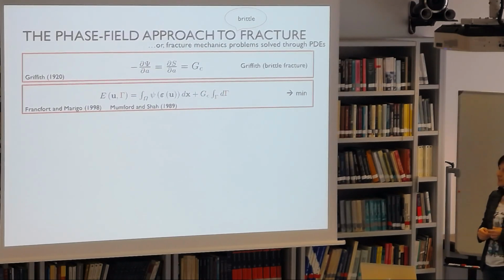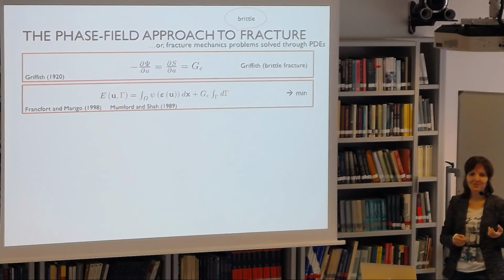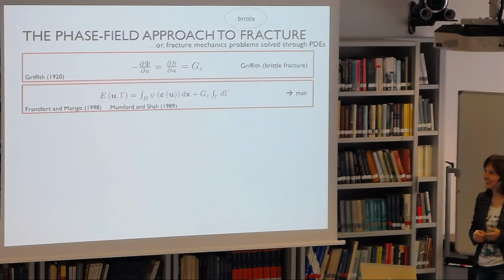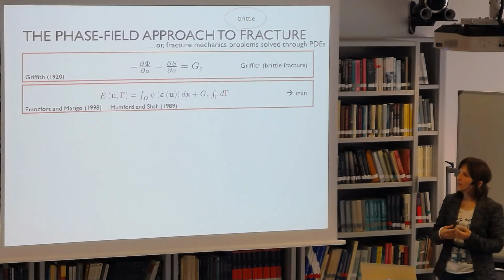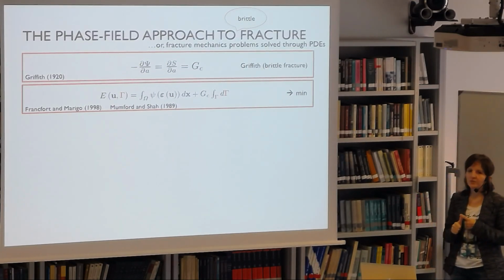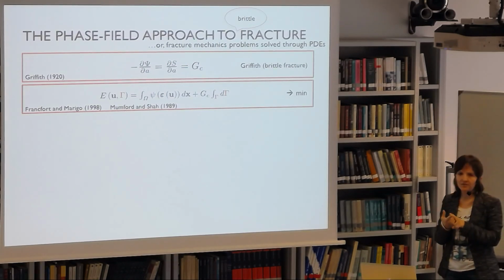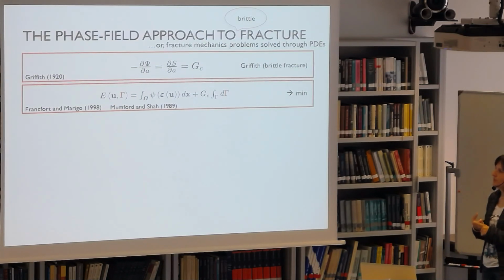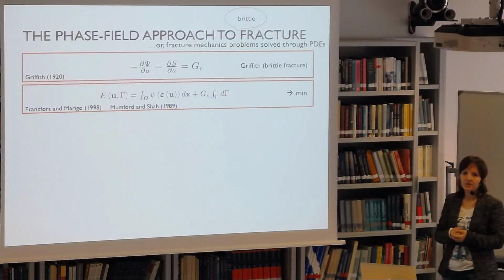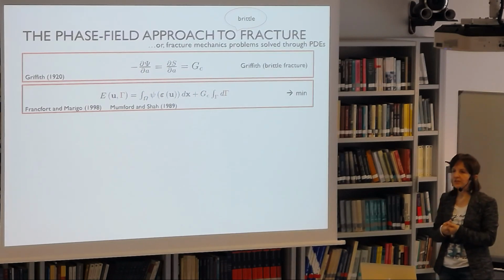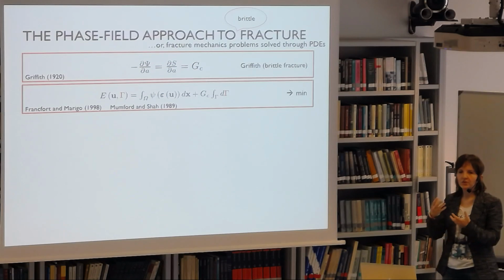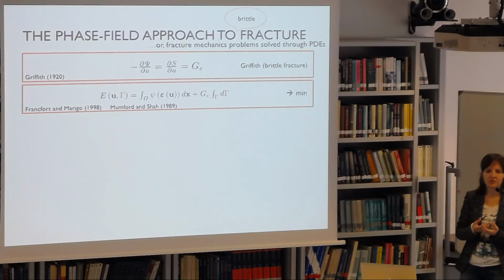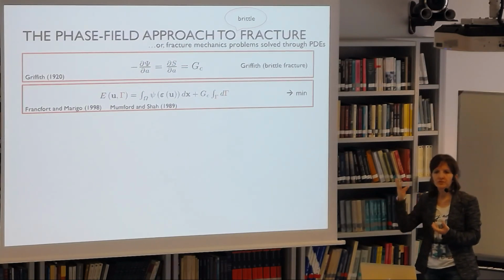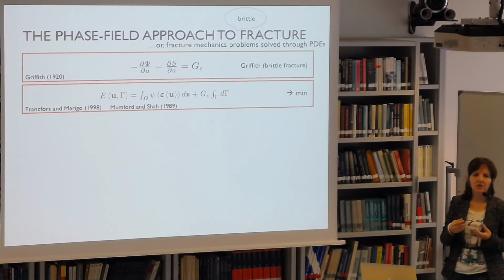Then at the end of the 90s, Jules Francfort and Jean-Jacques Marigo, who's probably very well known here, devised the variational approach to fracture. They basically recast Griffith's problem in the form of the minimization of an energy functional. Now, this energy functional has two arguments. One is u, the displacement field, and the other one is gamma, the crack set itself. So the energy functional is the sum of two terms. One term is the integral over the domain of the elastic strain energy density, and the other term is the integral over the crack set of the fracture energy. And since we postulated this to be proportional to GC, this is simply equal to GC times the integral over gamma of d gamma.